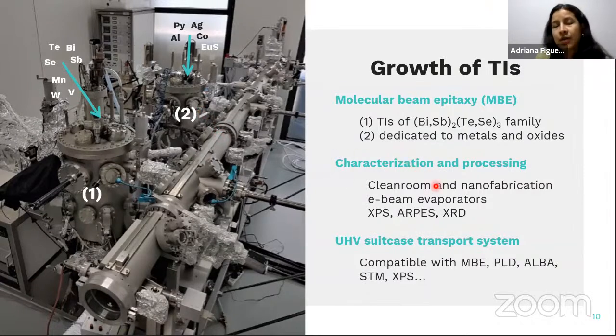And at ICN2 in our lab, we also have some important and relevant characterization and processing techniques, like a clean room for nanofabrication and characterization techniques for structural and electronic properties. And then there is another feature that I want to mention: we also have a system to transfer the samples that we grow in this chamber to other growth facilities in our building, for example, to grow by pulsed laser deposition other layers on top or underneath, and then transfer back in here. And we also have other characterization techniques like XPS, X-ray photoemission spectroscopy, or scanning tunneling microscopy, where we can transfer our samples grown here without breaking vacuum, using this UHV suitcase transfer system.